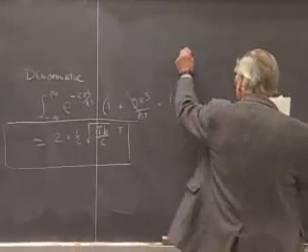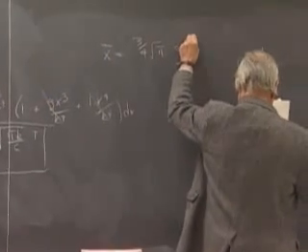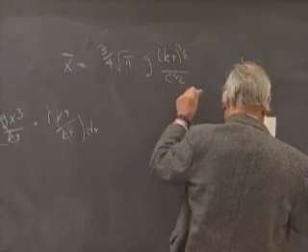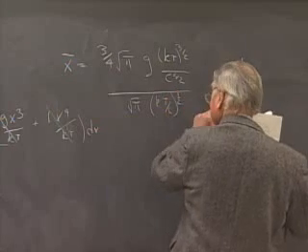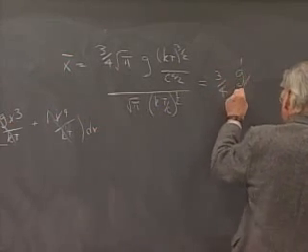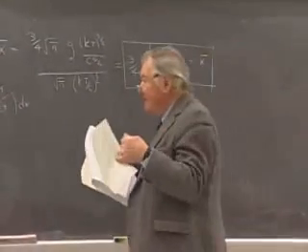And if I take the ratio of those two integrals, I have that the average value of x will be equal to 3/4 square root of pi times g times kt to the 3/2 over c to the 5/2 divided by the square root of pi times kt over c to the power 1/2. And if I carry through the algebra correctly, this turns out to be 3/4 of g over c squared times kt. Okay, so there is the average distance between this pair of atoms as a function of temperature in terms of characteristics of the potential.